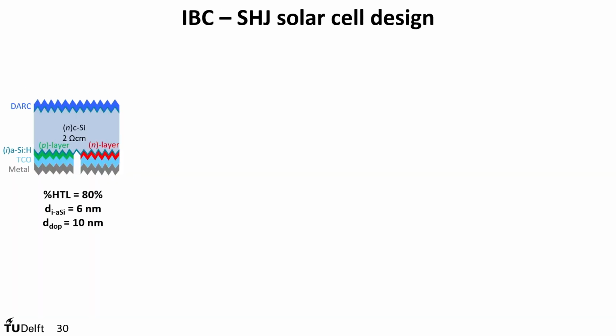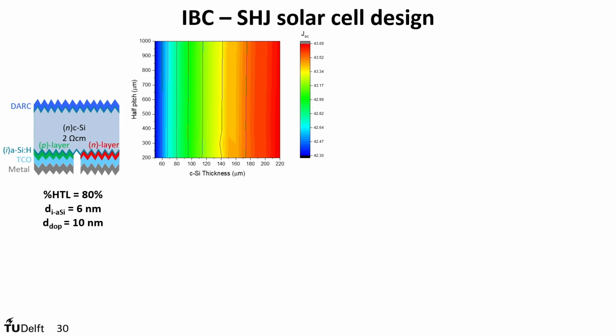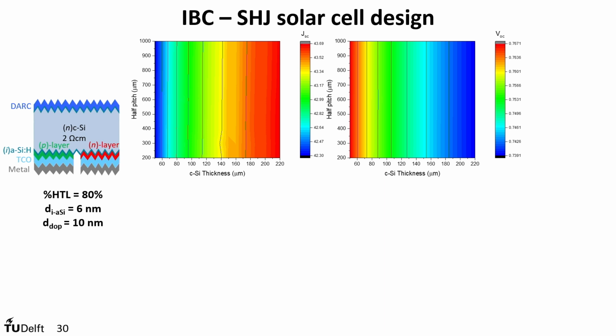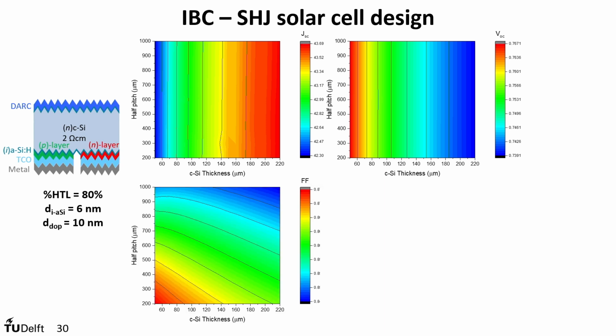Why do I do that? Because then, together with the intrinsic amorphous silicon and the doped layers thickness of 10 nanometers fixed, we can again make these heat maps where we combine crystalline silicon thickness versus pitch. And in this case, because it is an IBC, the way you want to optimize the JSC only depends on the thickness of the wafer. VOC goes in the opposite direction, nothing new here. And the only thing that changes, similarly to the case before, is that the crystalline silicon thickness for IBC devices has to be decreased if we want to push the efficiency further.